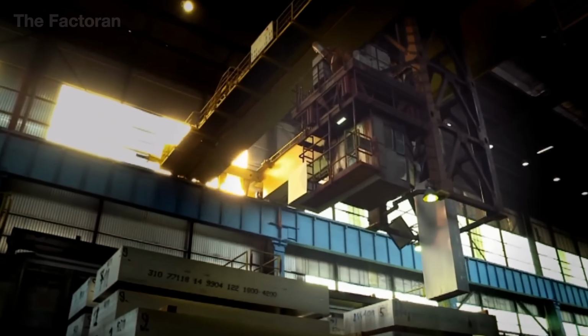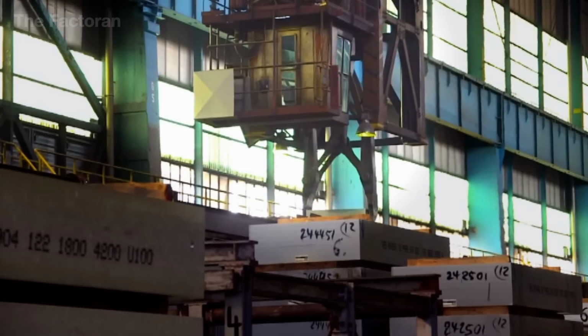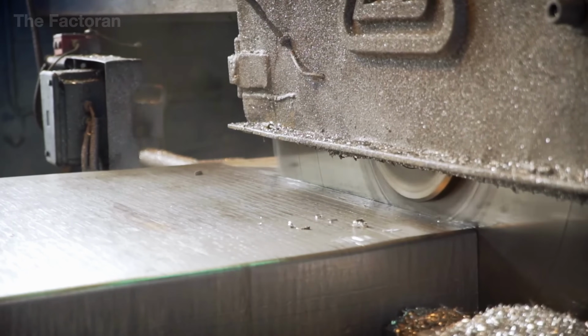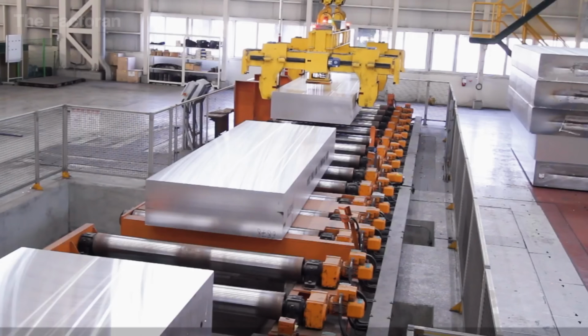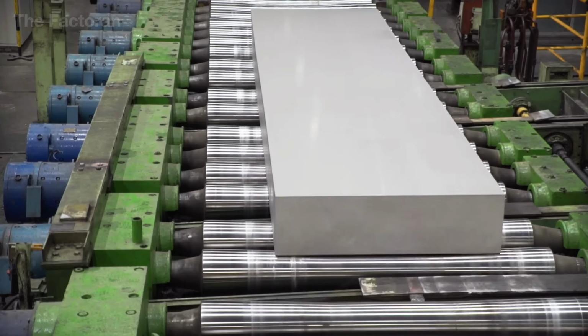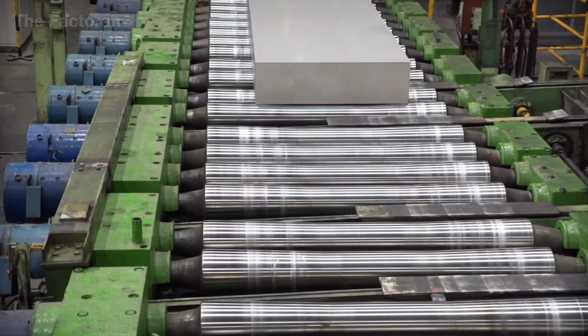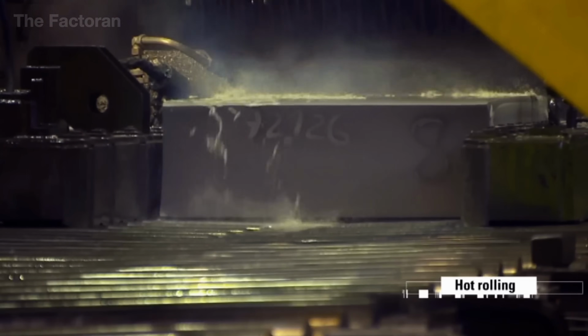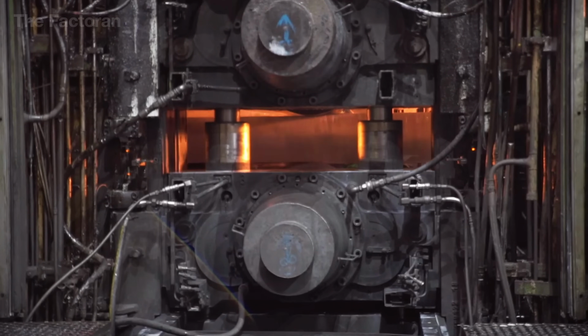At the hot rolling mill, massive solid billets of aluminum, about 10 to 15 feet long and weighing thousands of pounds, are loaded into giant furnaces maintained between 930 and 1020 degrees Fahrenheit. This intense heat softens the metal, increasing its malleability and reducing the risk of cracking during processing.